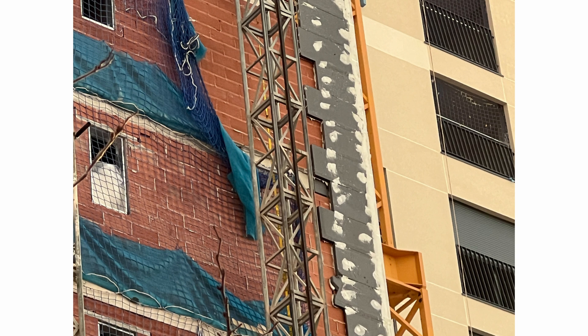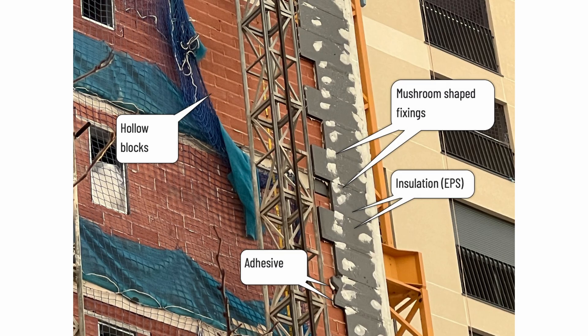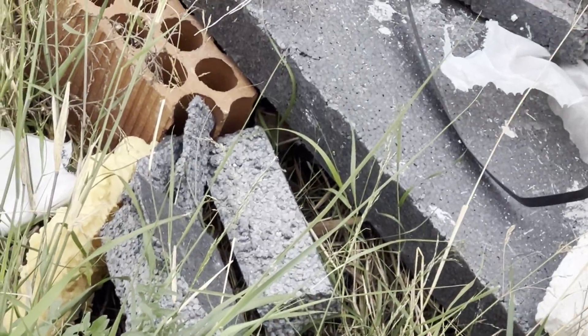The key word is composite, because despite its uniform, seamless appearance, it's actually made up of multiple layers. In the case of our Valencia building, the wall build-up consists of hollow clay blockwork forming an infill wall spanning between concrete columns and slabs, then a layer of dot-and-dab cement-based adhesive to pack out and level the insulation layer above. Then a layer of insulation — also fixed back to the blockwork with mushroom-shaped fixings — covered with an acrylic or cement-based coating to which a layer of mesh is applied. The mesh prevents cracking of the finished decorative top coat. In this case, EPS — expanded polystyrene — insulation is used.